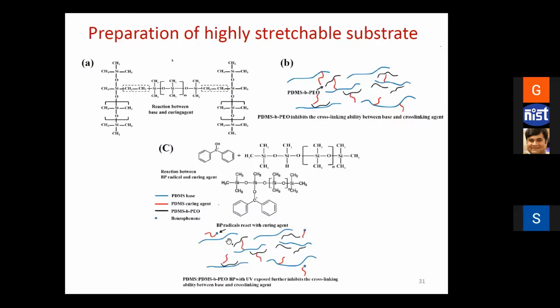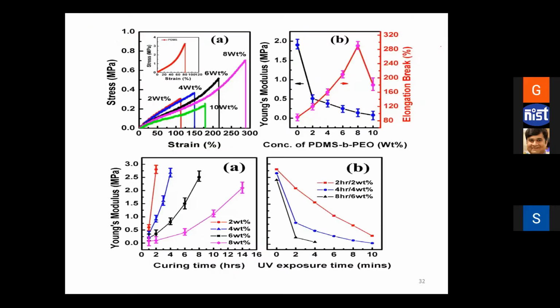What we did was that if you add PDMS-b-PEO to it, it basically inhibits the cross-linking ability between the base and cross-linking agent, right? And benzophenone reacts with the curing agent, and then it also affects its curing ability, and therefore it inhibits the cross-linking again. And we tried to use this approach, knowing this property of these materials.